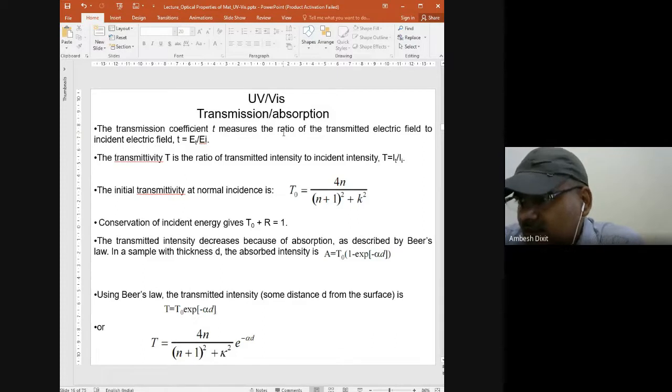So thin film, shiny samples which are more shiny on the surface are not advised to be measured this way. If I have a powder sample, you don't need to worry because it is a source of diffuse reflectance. Scatterings are huge, and you will get a reflected signal after scattering that has a much lower intensity. In that case it is advisable to work with.